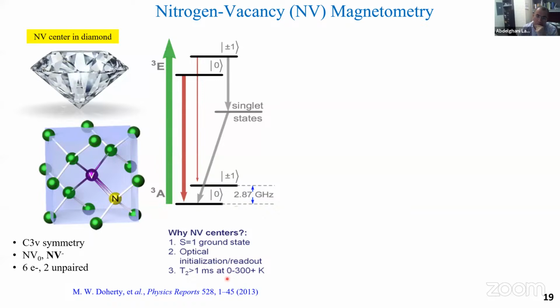Most importantly about this NV, the coherence lifetime of these spin states is very long. We're talking milliseconds in very isotopically pure diamond. And this can work at a wide range of temperatures, from 300 millikelvin up to demonstrations at 600 Kelvin or higher.